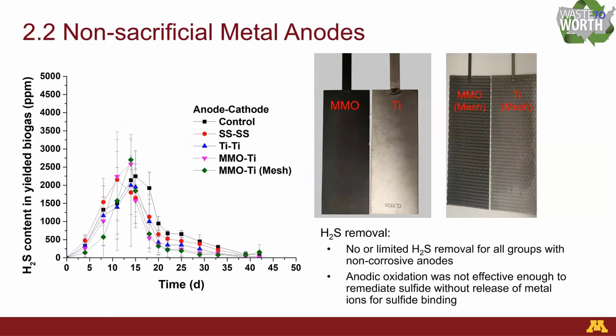Then, because it's sacrificial low carbon steel, we want to see if we can replace it with some durable material, so it can stay in the manure pit for a long time without changing the anode material or adding more electrodes. So we tested 3 different types of material, including stainless steel, SS, titanium, Ti, and mixed metal oxides coated titanium, MMO. But if we look at the results of the hydrogen sulfide removal, no or very limited hydrogen sulfide removal was recorded in all of the groups, which means these non-sacrificial anodes cannot remove the sulfide efficiently without the sacrifice or dosing of metal ions into the solution to combine with the sulfide. So pure anodic oxidation is not efficient enough to remove the hydrogen sulfide released from the dairy manure.